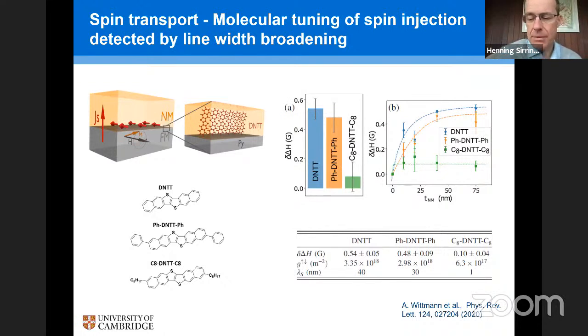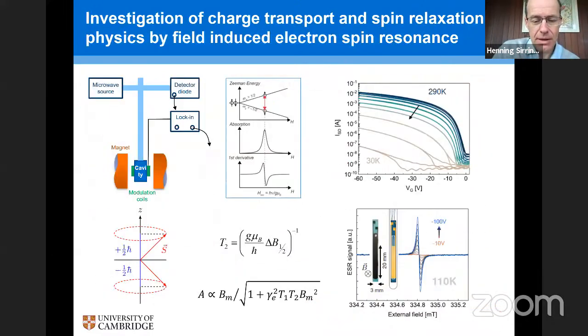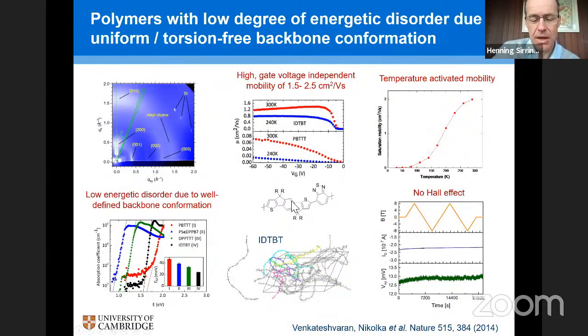Yes, that's a very good idea, and it's been a long-standing dream in a sense for people to have access to molecular systems like that, and synthetically they're not so easy to make. But we've recently had access to a system which Ian McCulloch's group had made, which essentially has no single bonds along the backbone. It's essentially just double bonded. I mean, it looks a bit similar to these fused ring systems. Maybe I should go to a different slide. If you look at this system here, our favorite IDTBT system has this fused ring structure, but then it still has single bonds along the main chain. And we've recently, through collaboration with Ian, had access to a system where these single bonds are replaced by double bonds, not in this system, but in a similar system.